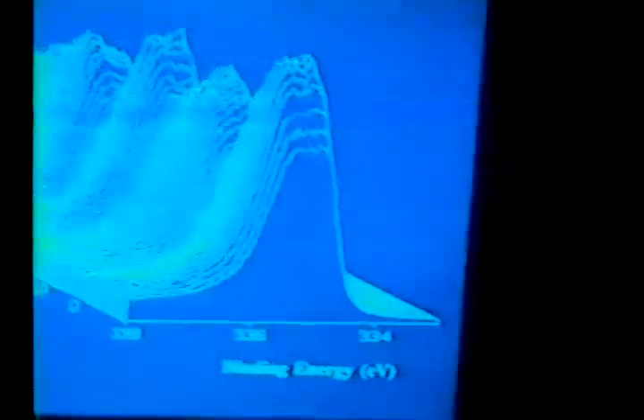of the 3d 5/2 palladium. This is the bulk palladium signal, which is there without oxygen. By the time the c(2x2) oxygen is added, one gets a new emission here, which shows high intensity at large takeoff angles. That indicates that this emission is a surface state, and we will call this bulk state and surface state.